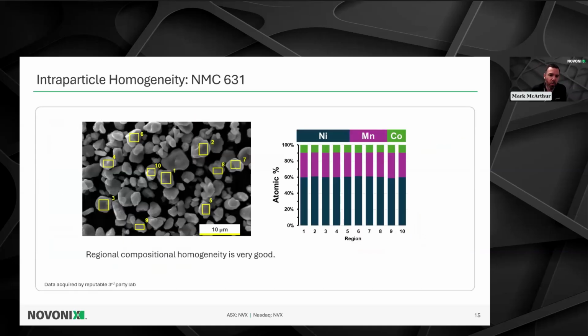Something that comes up a lot whenever we discuss dry processing methods for NMC is how do we guarantee that we are intimately mixing all of the nickel, the manganese, and the cobalt within the powder. This is called intraparticle homogeneity. And we leverage the methods of SEM and EDX quite frequently to really do elemental analysis of multiple components of the powder to demonstrate that, yes, indeed, we are getting the atomic ratios of nickel to manganese to cobalt that we expect. And in the case of 631, like I'm illustrating here, you can see in the bar chart on the right-hand side for 10 independent points that we do indeed recover that 60%, 30%, 10% ratio of the metals. So I would say here that, at least for this sample, the regional compositional homogeneity is very good.